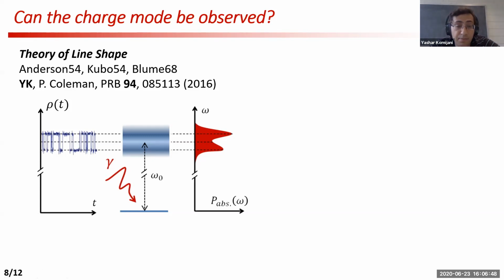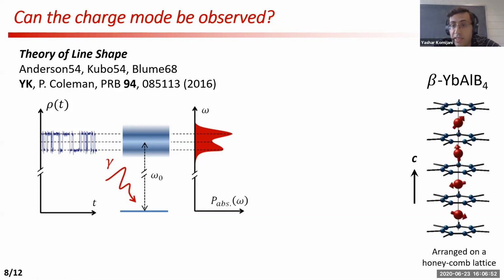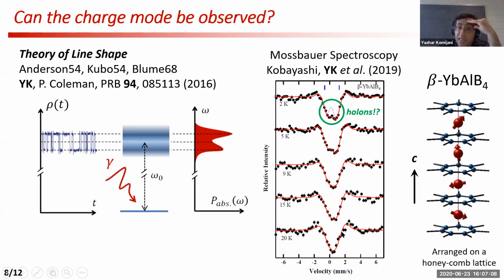Okay, and this idea has been tried recently on a different heavy fermion system. This is beta-ytterbium aluminum boron 4. It's also made of 1D chains of ytterbium magnetic moments, and the Mössbauer spectroscopy shows a dip. This is the nuclear transition, and this dip is supposed to get sharper at lower temperatures, but instead it remains broad, and it even maybe shows some sign of splitting. And so this looks a little bit similar to here. So we are speculating that maybe this is actually connected to these holons in the critical regime. So this material is critical at ambient pressure. You just cool it down and it's critical, and this is where this measurement has been done.